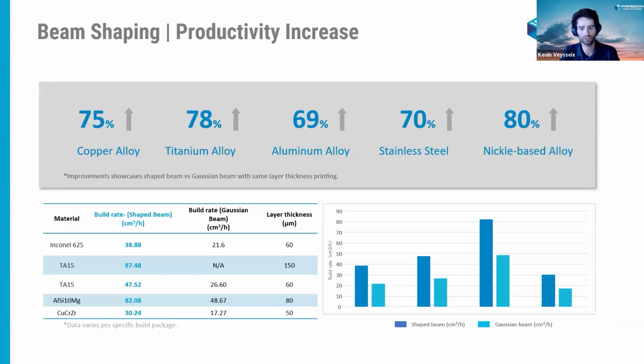So I was speaking about productivity increase. As I said, aluminum 69%. We were not even optimistic on this first number, because we see in Cornell, copper alloy, we even have a higher increase. And since it's written really small here, but it should be written big, we speak about the same layer thickness.